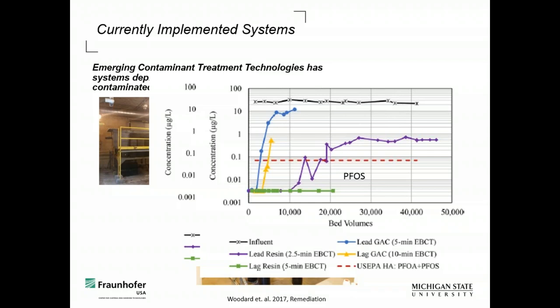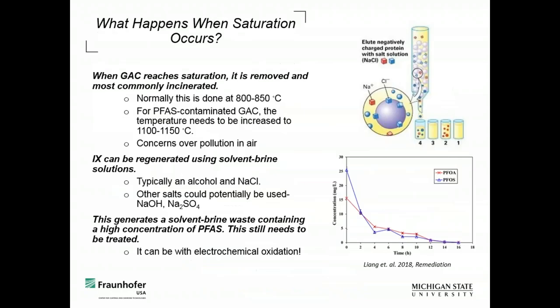Now, I don't think I put the shorter chain compounds in there. This resin does have a little bit of an issue with PFBA, so the perfluorobutanoic acid, the 4-chain carboxylate. So that's one Achilles heel of this, is that the 4-chain carboxylate is a little bit of an issue for them. I'm not an ion exchange expert, so I'm not exactly sure why that is, but it is something that they showed in this paper here.